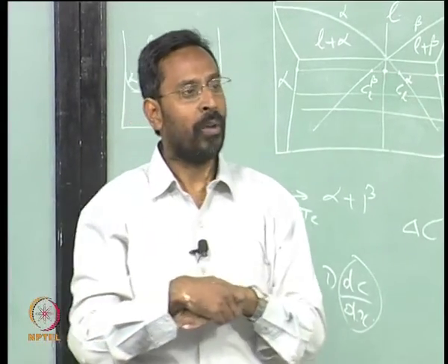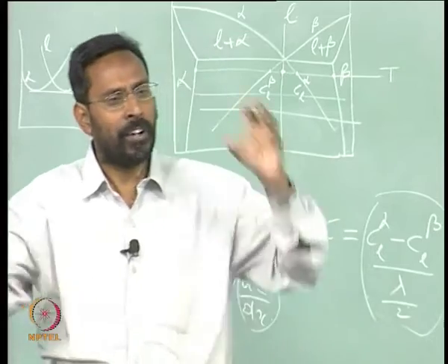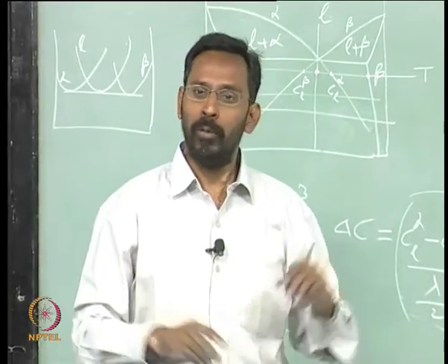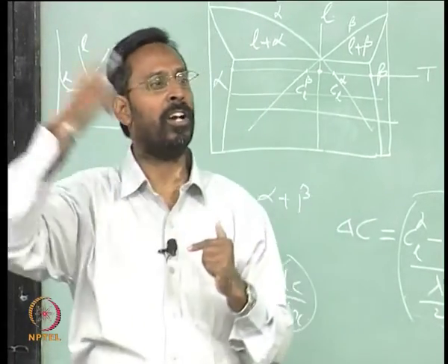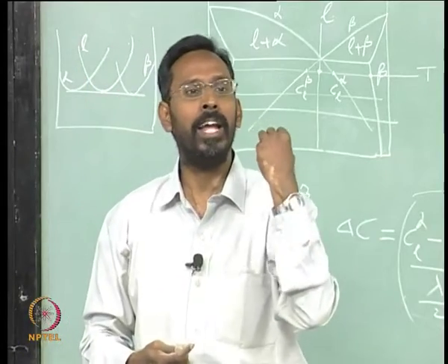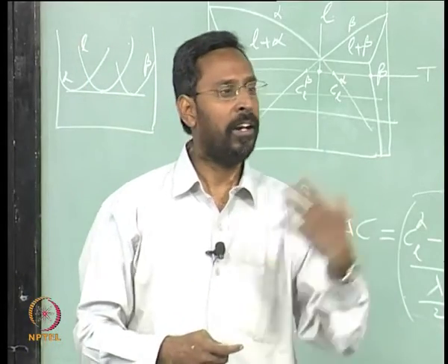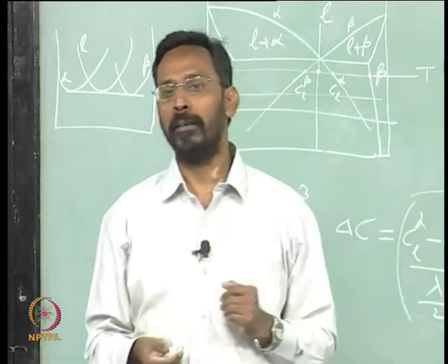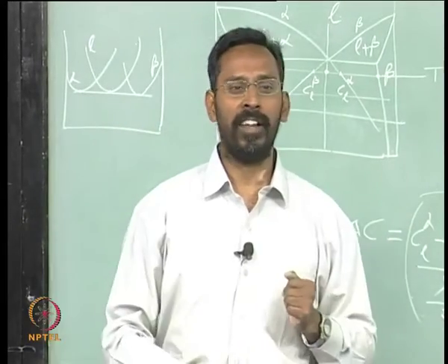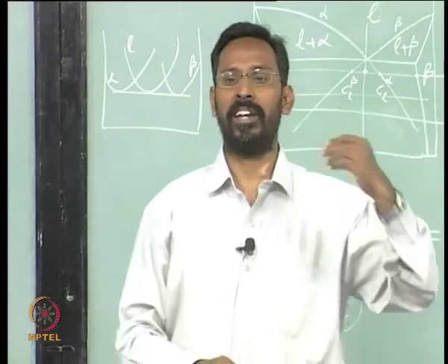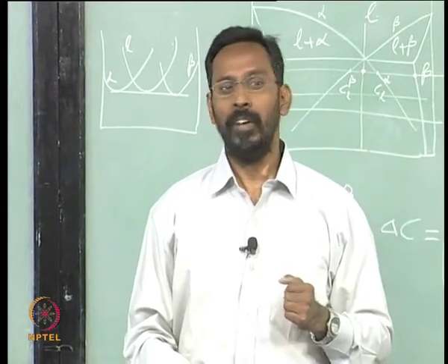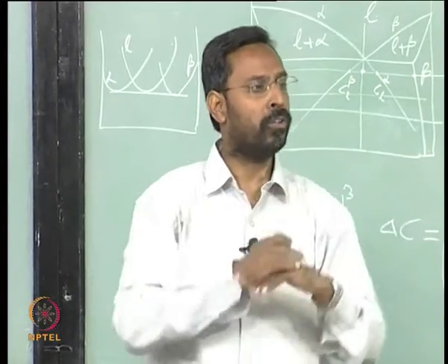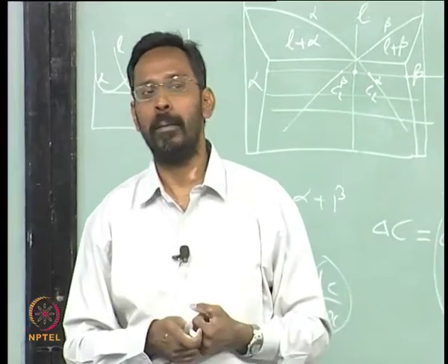That is why, when we talk about different particles being added, we look first at whether there is structural compatibility. For example, if I add a cubic particle into aluminum, titanium carbide is a wonderful nucleating site for aluminum because it is cubic - aluminum is also cubic, so it has easy compatibility.